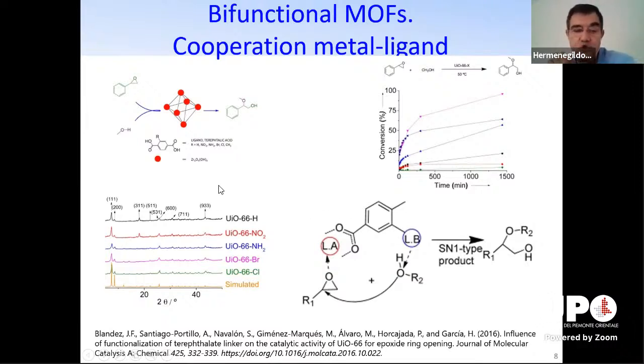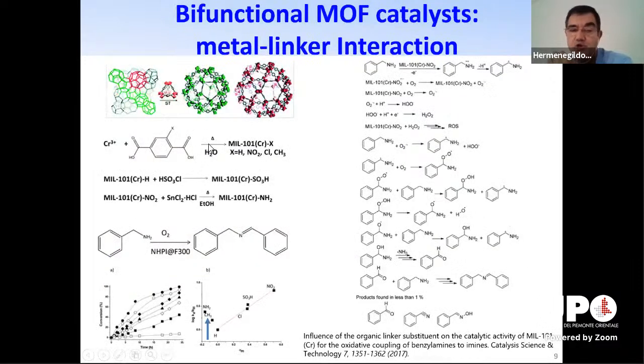So again, another example, this refers to oxidation, because what we have observed is that Lewis acids also catalyze oxidation reactions. This is an important point. So acidity can be used to activate oxygen. For instance, here is the full reaction mechanism, in which the active site generates a radical, and this first radical that is generated then drives all the oxygen activation. And really what we have is a chain reaction mechanism.